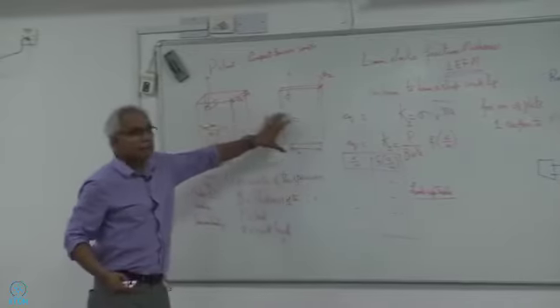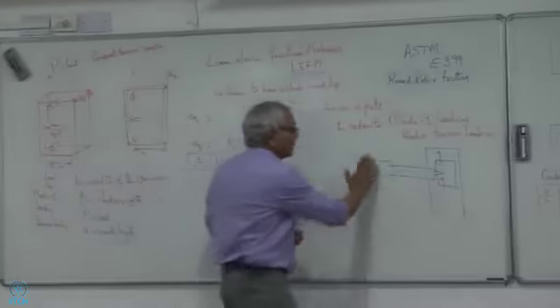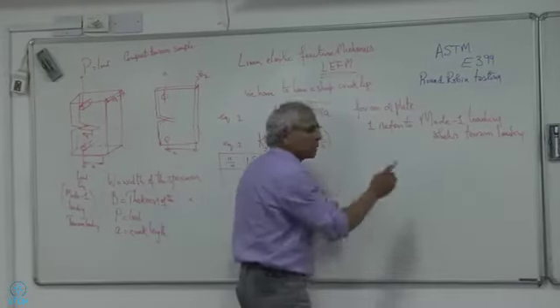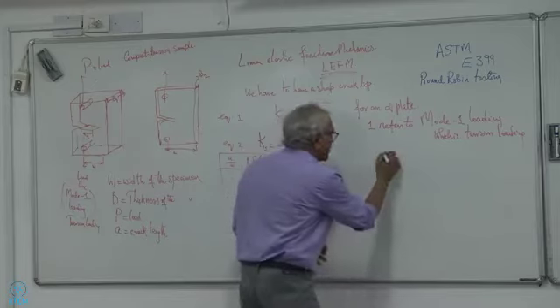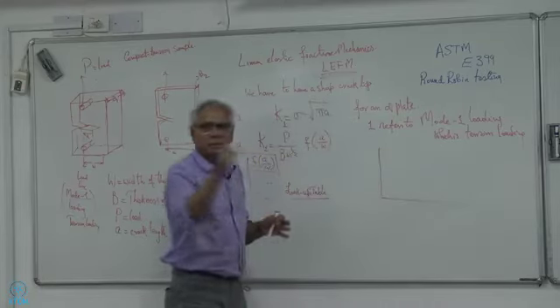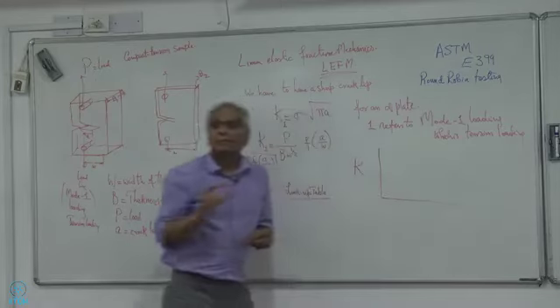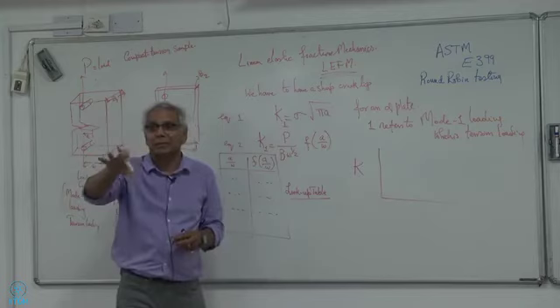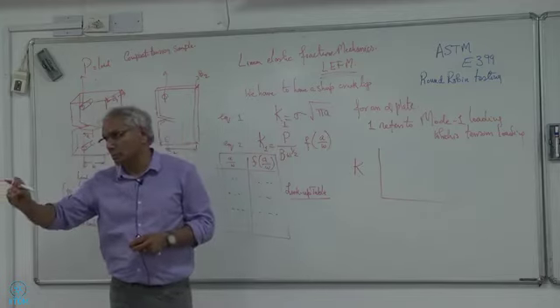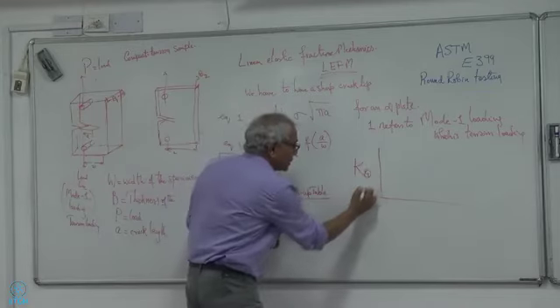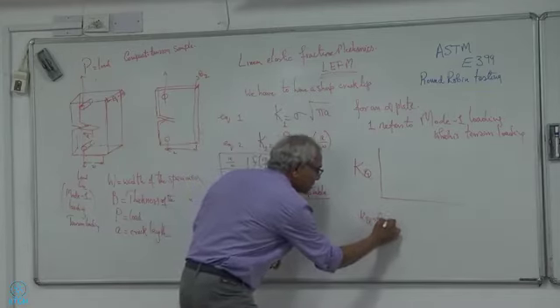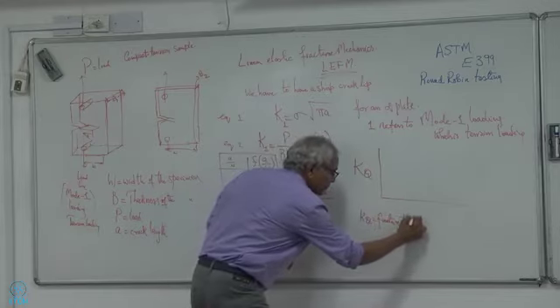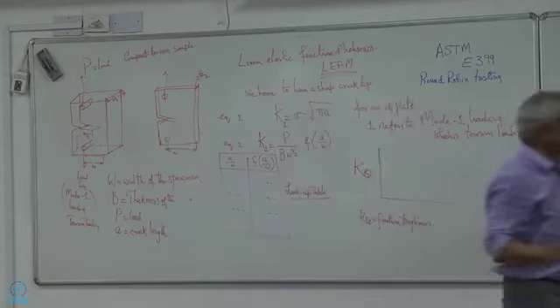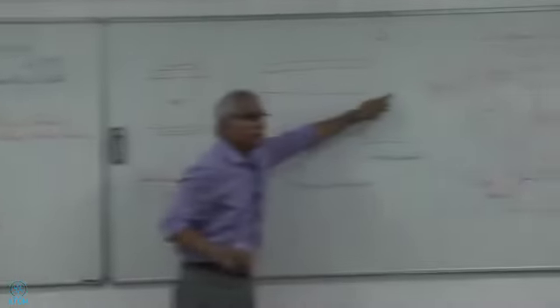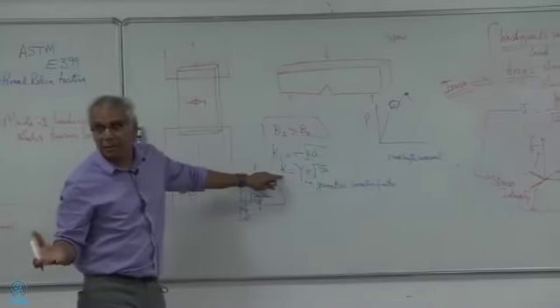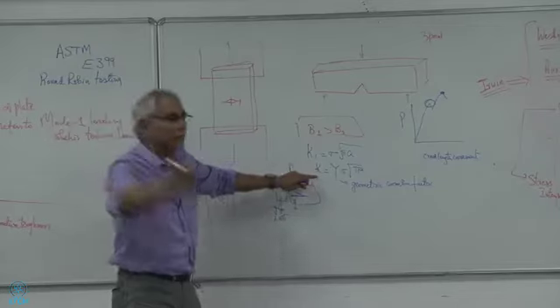So here is my thick sample, here is my thin sample. This is what I'm going to do. I can explain things better this way. If I plotted what you just said, fracture toughness, I'm not going to call it K1C or K sub C. Let me call it K sub Q. So K sub Q is my fracture toughness. Did I define the fracture toughness? Probably not. When this crack length became critical, my K becomes critical. That critical K is my fracture toughness.